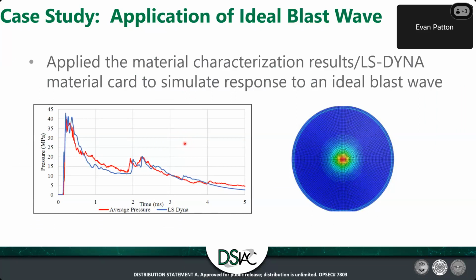The overarching case study test objects were essentially a hybrid panel: a stack of that PET glass fiber composite glued to an aluminum face sheet. I apologize, I don't have any experimental results or figures because I didn't want to dive too much into that aspect. Basically, we set those test objects in an open-ended blast tube and tested them with this pressure curve, which was both experimentally recorded and modeled in LS-Dyna. On the right-hand side is a pressure distribution contour map of the actual specimen. Those specimens were, I believe, 7-inch, fully circularly clamped specimens, with the nozzle right in the red area.